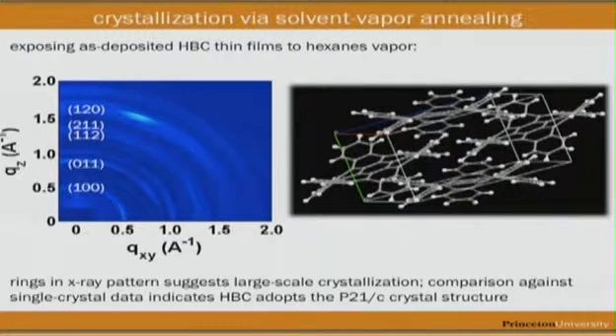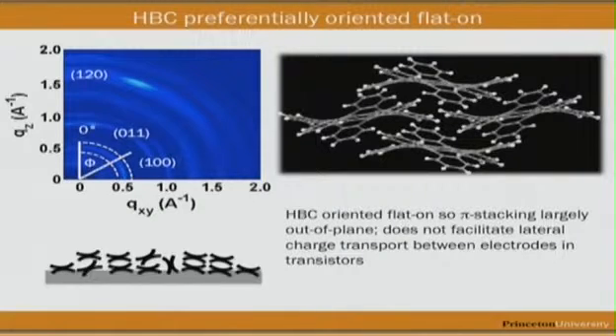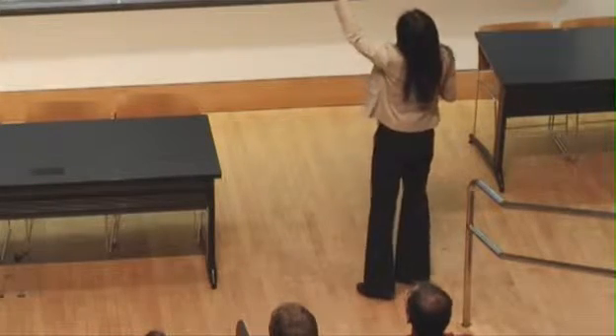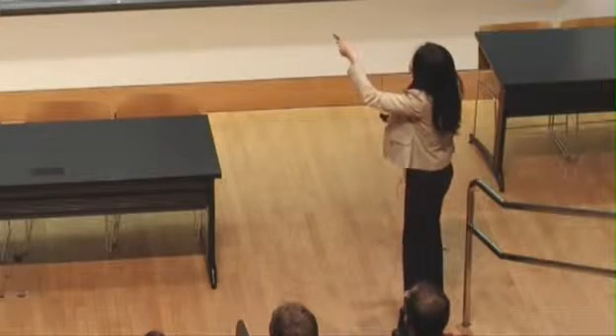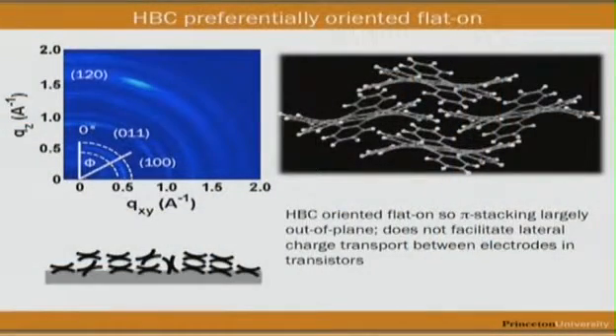We can take this X-ray diffraction pattern, and we can run through our analysis, and we can plot the intensity as a function of azimuthal angle. Okay? And using that data, we can compare it against our single crystal data. And what we figured out, what Anna figured out, is that these molecules are actually oriented flat on, so like I've cartooned here. Okay? And so when the molecules are oriented flat on like this, the pi stacking direction is generally in the vertical direction. So it's no wonder that this film, although it's crystalline, the mobility is not that much higher than the mobility of a device that has these amorphous films.